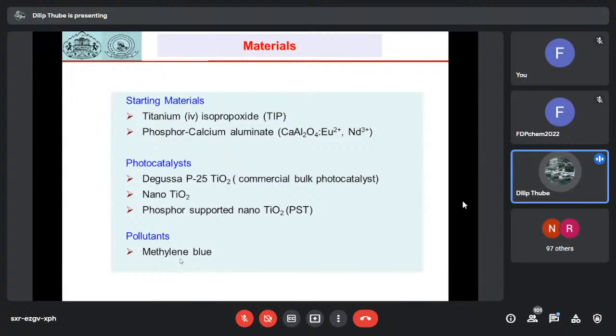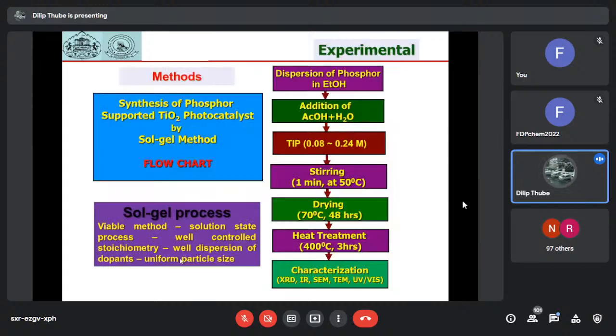So in a very simple way, the supported TiO2 can be synthesized. Most of our laboratories have titanium isopropoxide, as well as calcium aluminate phosphor material, which can be doped with europium, dysprosium, as well as neodymium. The photocatalysts utilized in this process are a commercial sample, Degussa P25 TiO2, a nano TiO2 sample prepared by the same method, as well as phosphor supported TiO2 material. And the model pollutant used is methylene blue.